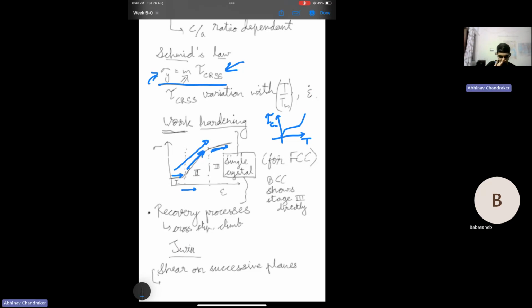So all this will occur. Kinks, of course, are immobile, so they are also a form of major obstacle. And because of all this obstacle creation, the mobility of dislocations will reduce. You'll have to apply more stresses to make them overcome these obstacles. So we'll have a very high work hardening rate.